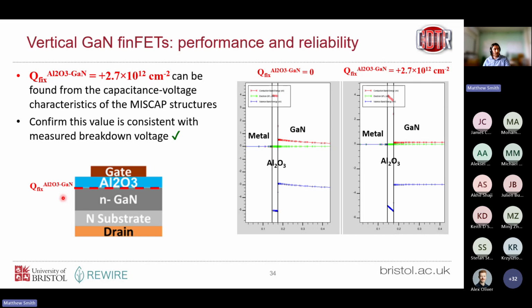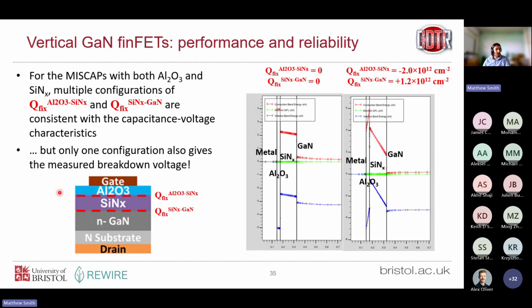We can use simulations, again a Silvaco simulation, to find the band diagram when we have 0 fixed charge and some non-zero amount of fixed charge. We can see how that changes our band diagram here. And what we can actually do is look at our experimental flat band voltage and our experimental breakdown voltage and find this value of fixed charge at this interface. So quite straightforward there for this structure.